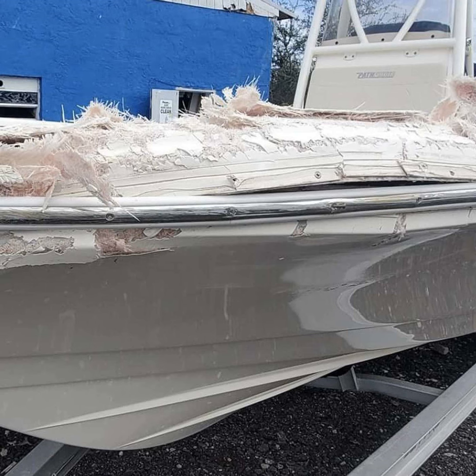One of the things you can do once you grind all the gel coat off is spray some acetone onto the damaged area. Just for a second or two before it evaporates, it really helps to make the fiberglass transparent and highlight what damage you have. If you're looking at cosmetic damage, you're going to be looking at things like scratches in the surface, chips and gouges, things that are obviously from a specific incident, like a scratch there, or a little gouge from the dock, or gouges on the keel from maybe some oysters or something like that.